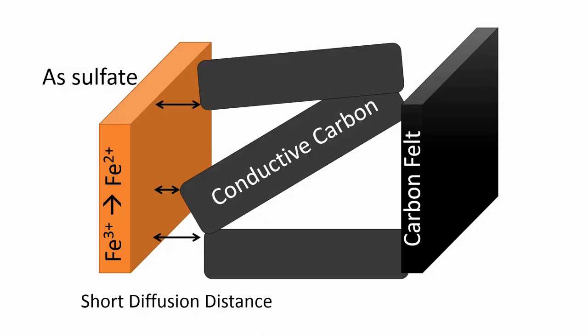We tried this and found that it was really slow to give up those electrons. Really high resistance, so we worked hard to fix that. We found that if we use a whole bunch of conductive carbon, it produces a shorter diffusion distance and much better current, even without necessarily the most optimal chemistry.